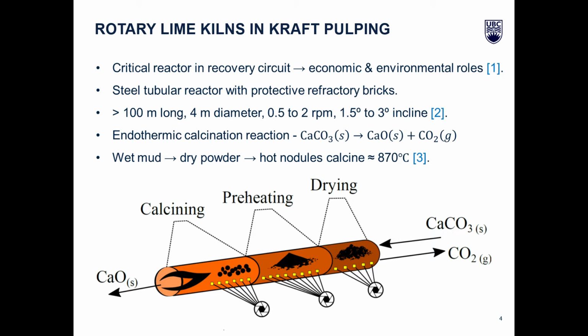Kilns are inclined at around 2 degrees and rotated by a drive gear to allow solids to move through the kiln. Wet lime mud enters the kiln where it dries into a powder and preheats before agglomerating into nodules that then undergo calcination, converting the calcium carbonate into calcium oxide and carbon dioxide. Calcium oxide nodules exit at the firing end of the kiln, where they are then used to regenerate white liquor. The figure on this slide illustrates a kiln that has been outfitted with thermal cameras to collect shell temperature measurements.